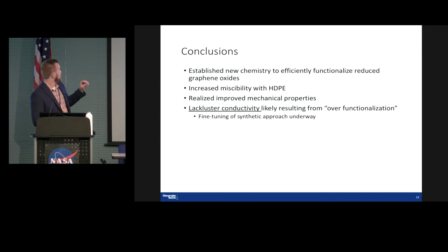So in conclusion, some of the points I want to drive home: one of the things that we're proud of is that we've established new chemistry to efficiently functionalize these materials. This reaction scheme had not been done before, and it opens up a lot of new opportunities for us to modify these graphene oxides in other ways. And I'll talk a bit more about that in just a second. As I alluded to, we increased the miscibility with high-density polyethylene. We have so far been able to show that we've improved some of the mechanical properties. However, the conductivity is really what's hurting the performance of this composite so far, and we believe that's a result of over-functionalization.